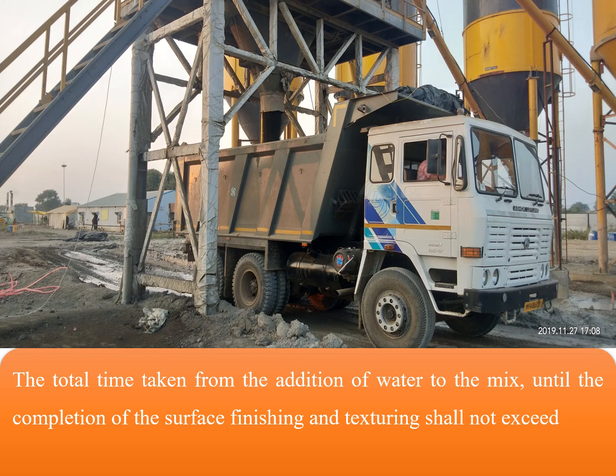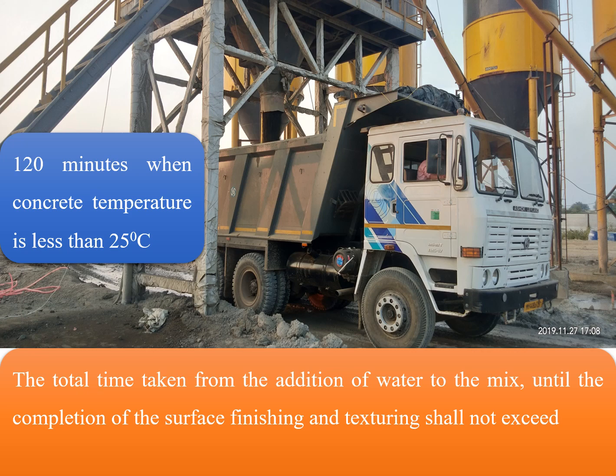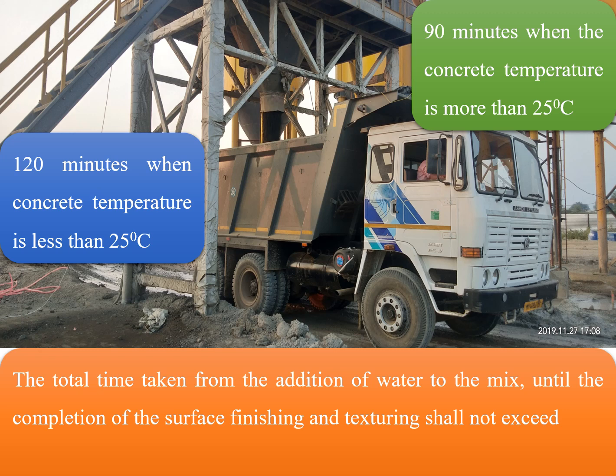The total time taken from the addition of water to the mix until the completion of the surface finishing and texturing shall not exceed 120 minutes when the concrete temperature is less than 25 degrees centigrade, and shall not exceed 90 minutes when the concrete temperature is more than 25 degrees centigrade.